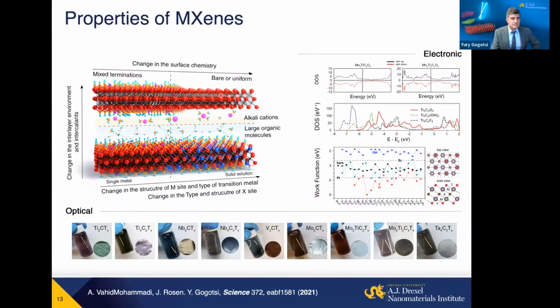We can use carbon, nitrogen, make carbides, nitrides. We have a dozen transition metals to choose from. And we have surface termination. It's also possible to make bare, non-terminated structures, but of course they can only exist in high vacuum, because transition metal will immediately capture oxygen and other molecules from air when exposed.